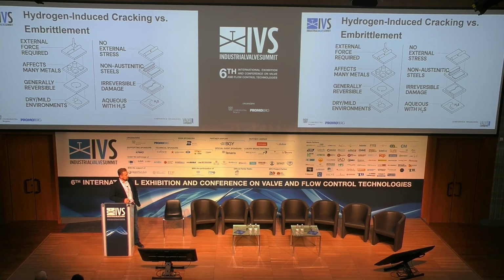After that, we can talk about hydrogen-induced cracking. I saw some papers that talked about embrittlement and cracking like they're the same thing. They're not. There are two different mechanisms, two different phenomena that cause similar damages, but there's one very big difference that most people ignore. In some cases, embrittlement can be reversible. In some cases, the cracking isn't reversible. Once it's cracked, it's done. You need to change the piece. And basically, the cracking doesn't occur if there's no external force.